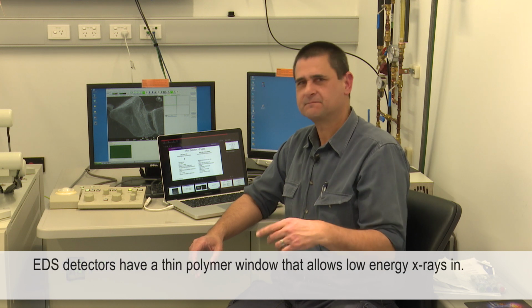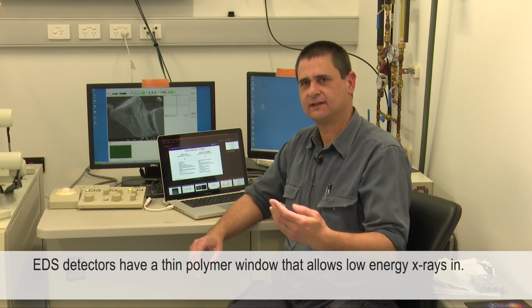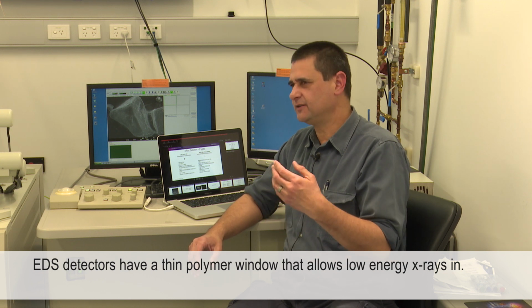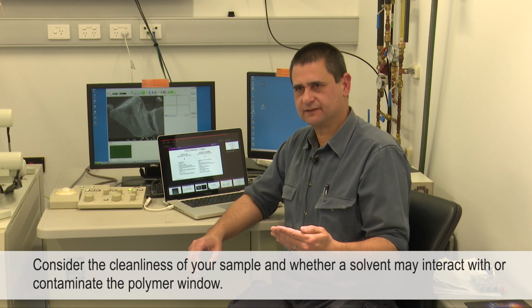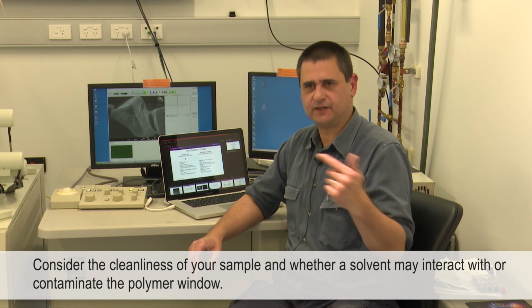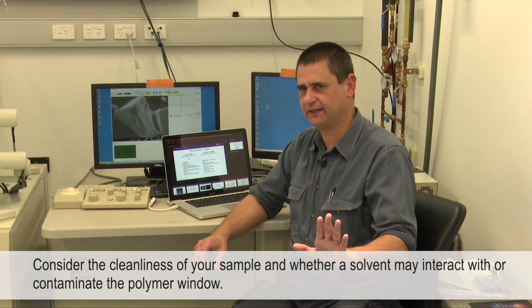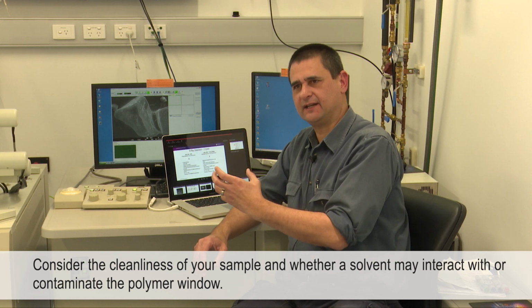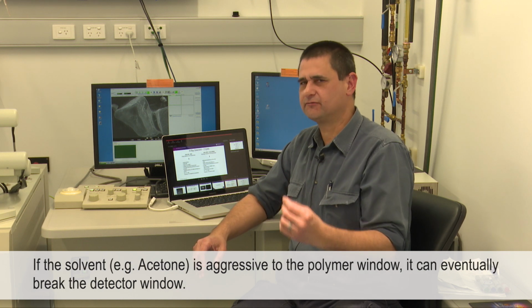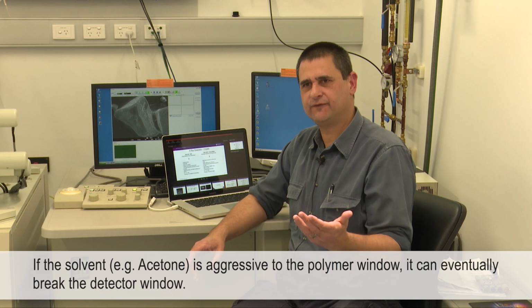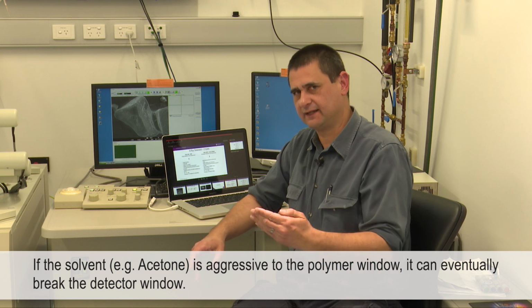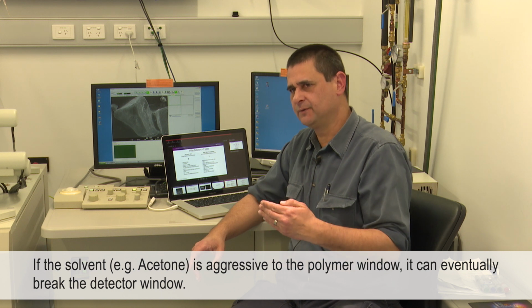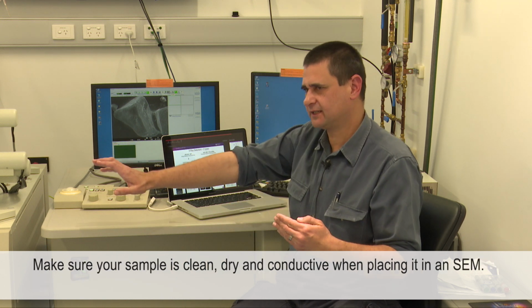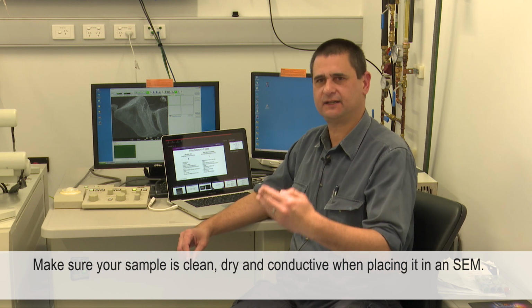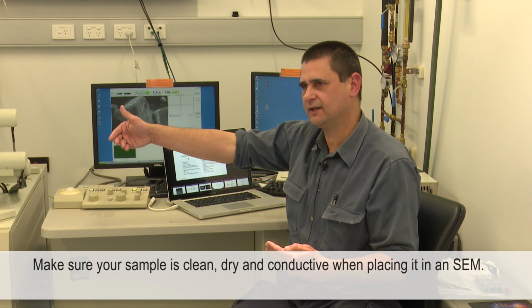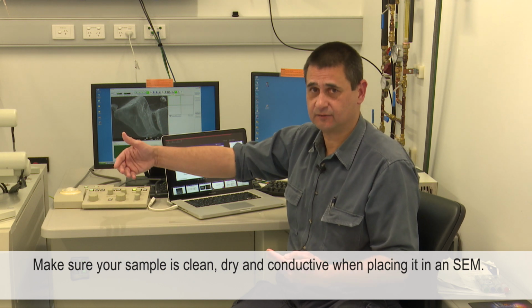That's my EDS detector. My EDS detector has a thin polymer window on it to let low energy X-rays in. If you use some not nice solvent and you don't properly dry it out before you go to the SEM, and remember cleanliness is important in the SEM, that solvent contaminates my detector. If that solvent is aggressive to a polymer, such as acetone, you eventually break my detector window. And I've seen that happen to multiple detector windows, people not taking care of them, not because they physically touched them, but because they never took care of the cleanliness of their specimen, contaminating the detector window or actually breaking the detector window. It does happen.